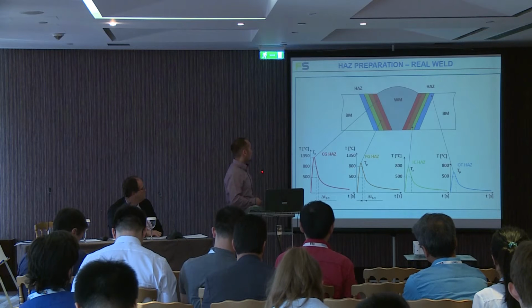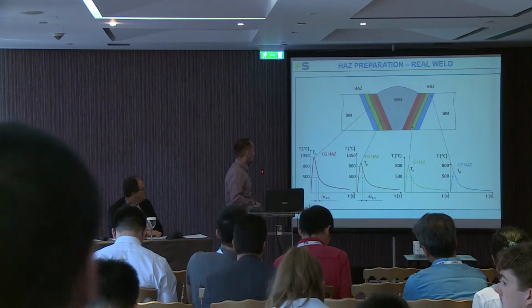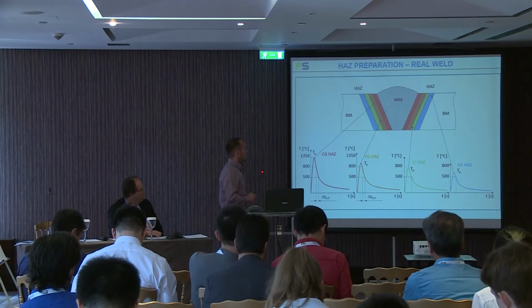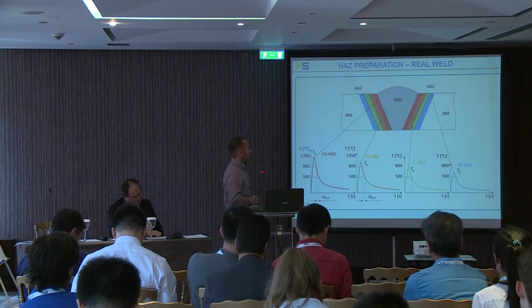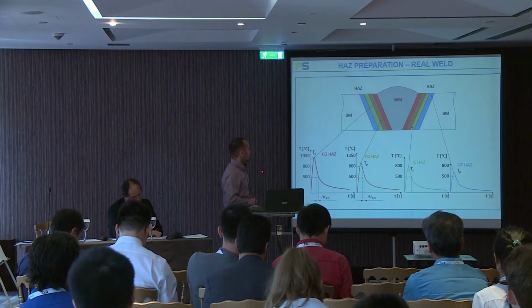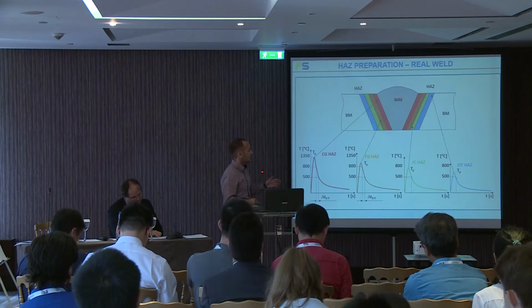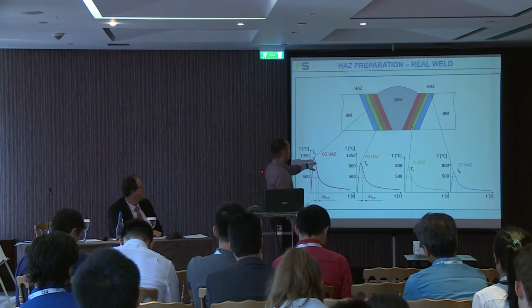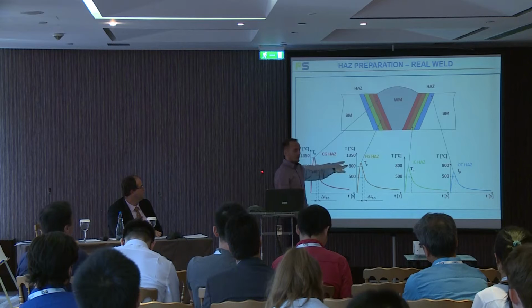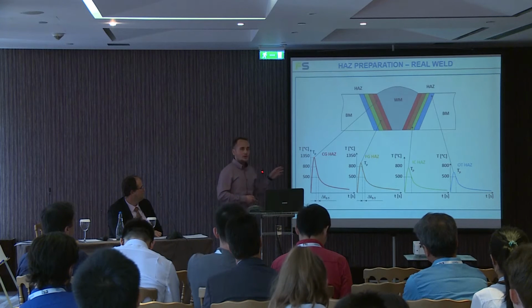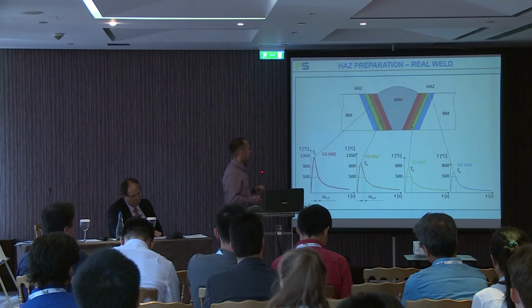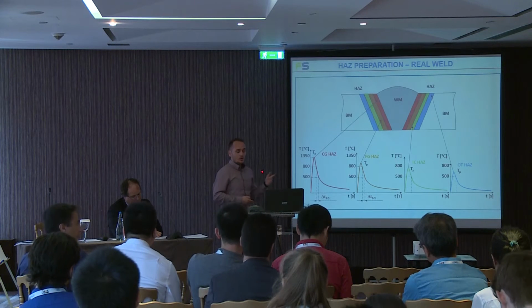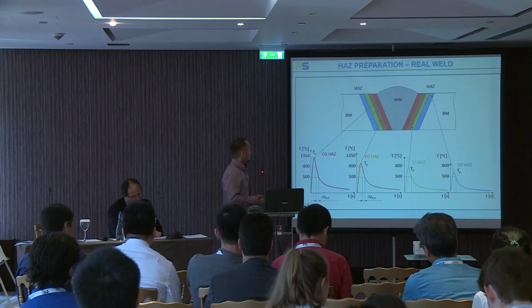If we know the thermal cycles of the heat affected zone, we know that it is divided into sub-zones, like coarse grain heat affected zone, fine grain, intercritical, and over-tempered heat affected zone. Our focus was on coarse grain and fine grain. We have prepared specimens in such condition to make different tests, such as the tensile test, Charpy, and fatigue also.